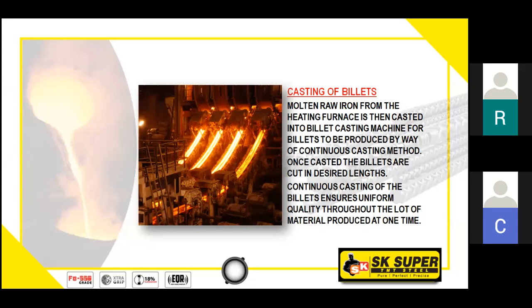So once the billet starts to come out of that billet bucket, it comes in a long length, which has to be cut as per the required lengths. Now at this stage, the temperature drops from 1650 degrees to 1100 to 1150 degrees. When the billet is coming out of the bucket, you might have seen that water is sprinkled on the billet just to cool it down and bring it to the temperature of 1100 to 1150 degrees centigrade.